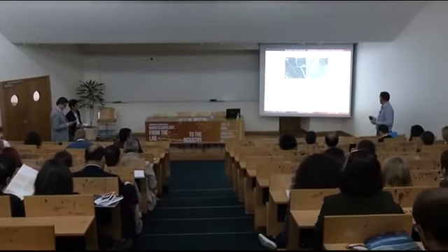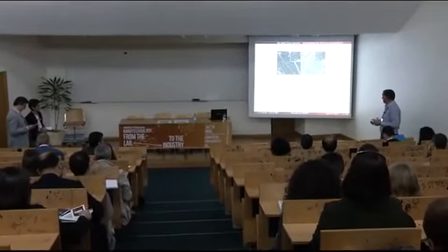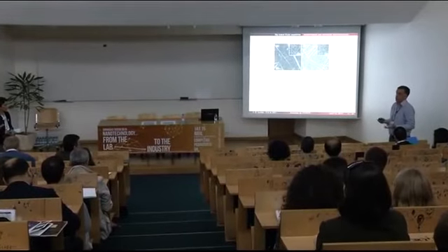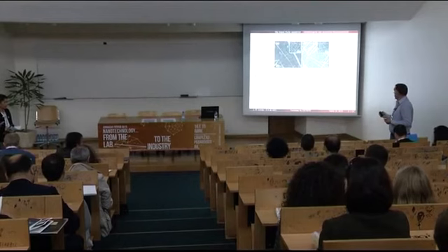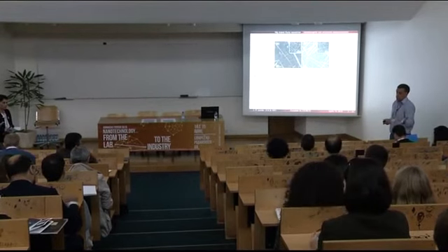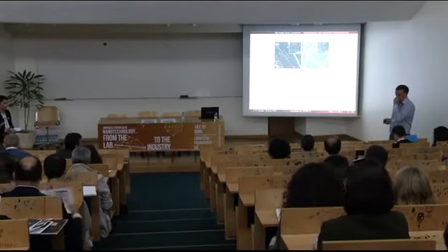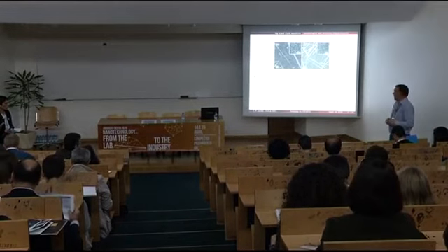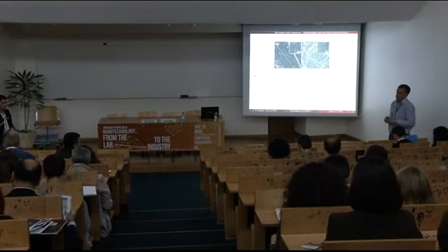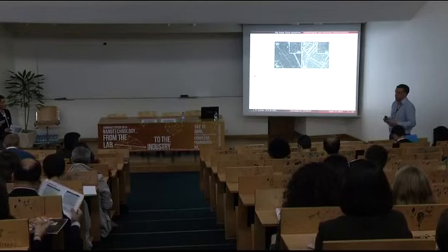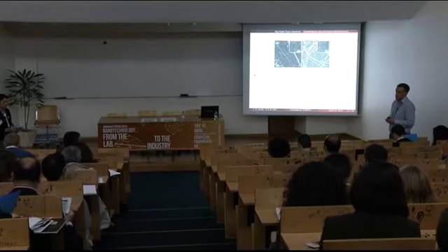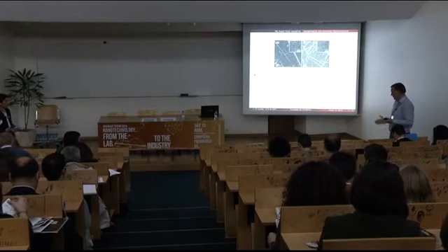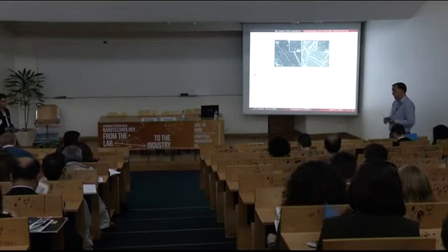In this case, in terms of technology, the most important case is the growth on silicon. We have the lattice mismatch between gallium arsenide and silicon. So probably we have polycrystalline epilayers, which is a problem for the vertical alignment.